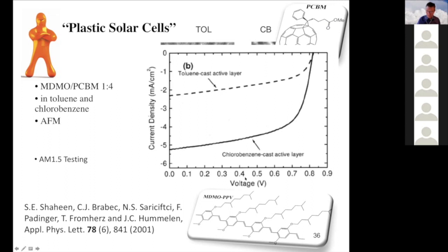This is a current-voltage plot. If you shine light on the film cast from toluene, there's not a lot of current, but you can generate more than half a volt. If you take the other layer, then a lot more current is generated, almost twice as much. The voltage is basically almost the same, so that's related to the material properties, but the current is much higher. So that is influenced by the nanoscale morphology.